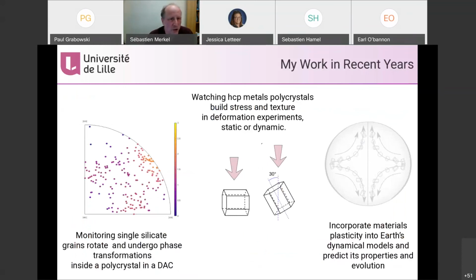What I tried to show you in this talk is how we use multi-grain X-ray diffraction to monitor single silicate grains, how they rotate, and what happens when you go through a phase transformation inside a diamond anvil cell. You can also watch grains of HCP metals in polycrystals in real time, and how they build stress and texture in deformation experiments, static or dynamic.